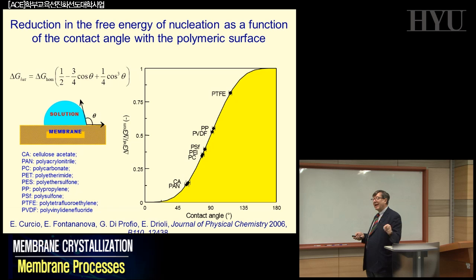So the membrane was not only acting to evaporate, it was also inducing a change in the activation energy controlling the kinetics of crystal growth. If you check the literature, there is the difference between the Gibbs free energy of the heterogeneous system compared to that of the homogeneous system. Homogeneous is traditional crystallization when you are working in a solution. Heterogeneous is when you are on the membrane surface. Already people were expecting quite an interesting effect in the reduction of the heterogeneous activation energy. That means the difference between the Gibbs free energy of the heterogeneous compared to the homogeneous one.